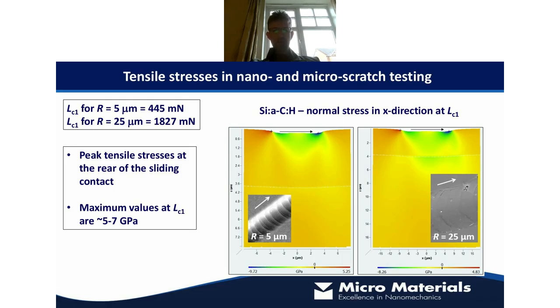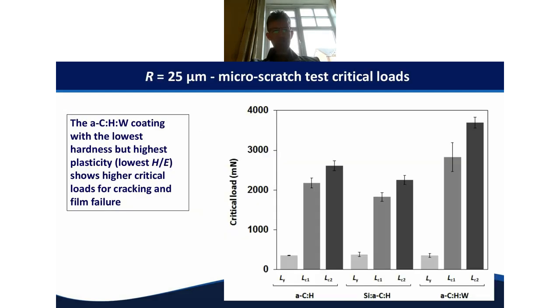We can also look at tensile stresses. These form at the back of the sliding probe. You get this maximum here at the back. And you can see that even though the critical loads in nano and microscale scratch tests are quite different, they actually correlate to quite similar tensile stresses in these tests, suggesting that there's basically a similar mechanism, or the same mechanism, going on.